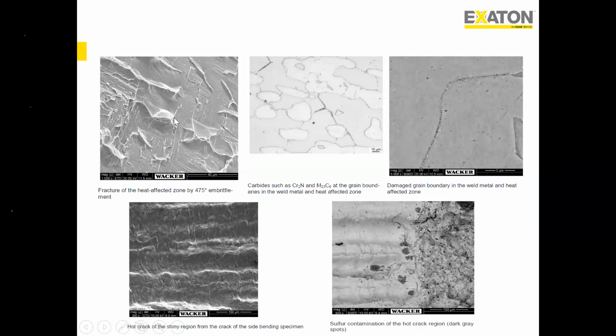So we did the same analysis on that, and we found this. We also found carbides, basically chromium carbide or M23C6, formed at the grain boundary in the weld metal as well as the heat affected zone, which basically damaged the grain boundary in the weld metal and heat affected zone. This is the area. Hot cracking: the shiny region from the crack on the side bend specimen. So we did SEM, and we found that the shiny things are basically the evidence of hot cracking. We also did some chemical analysis and found there was sulfur contamination of the hot crack region.